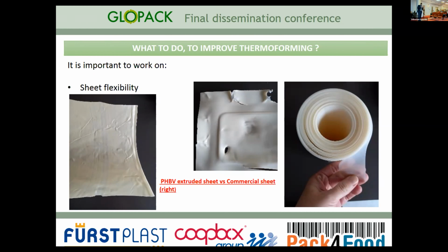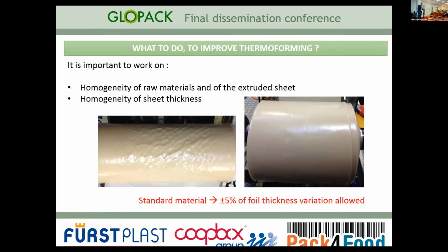The commercial sheet that we used at the beginning was quite flexible. So it's something that we have to work on, to have a better production and to scale up the production. Another issue is the homogeneity of the sheet. Homogeneity is considered in two different definitions. The first one is that the thickness of the foil has to be even across the whole width, because in this way all the trays that are produced have the same characteristics, the same thickness. It's needed for the industrial process to have a good distribution of the material inside the sheet and also inside the trays.